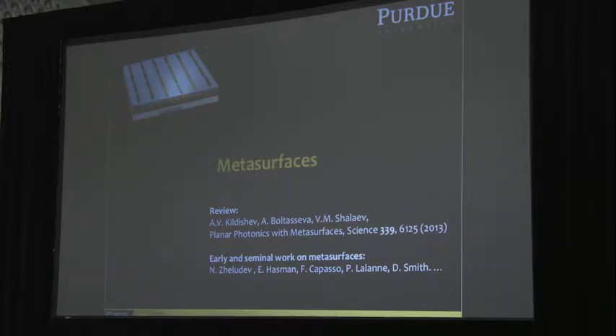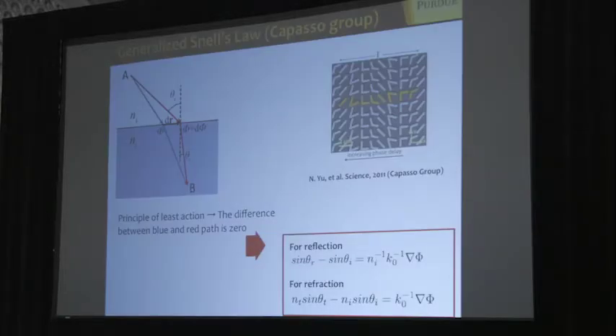And of course, as always happens, there was lots of early work in this area done by E. Hasman from Technion, for example, Philippe Lalanne, but Federico Capasso, I should say, made a difference with his pragmatic technology-driven approach when he demonstrated really lots of devices using this notion of metasurfaces. So, I mean, the idea is really straightforward. Normally, when we look at the way light is refracted at an interface, the longitudinal component of momentum should be conserved. As a result, if refractive index is higher, the light bends toward the normal, the Snell's law. But that, of course, assumes that there is no phase gradient along the interface.